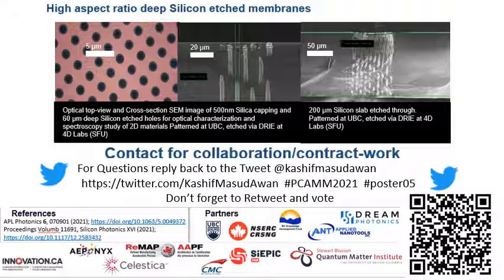So we patterned it using the laser direct writer, which is the Heidelberg lithography system I talked about earlier. And then we etched the silica layer first using dry etching, and finally we etched the deep silicon using DRIE at 4D Labs at Simon Fraser University in Vancouver.